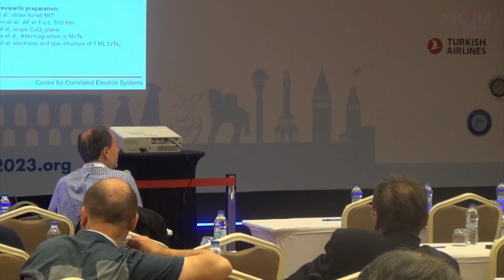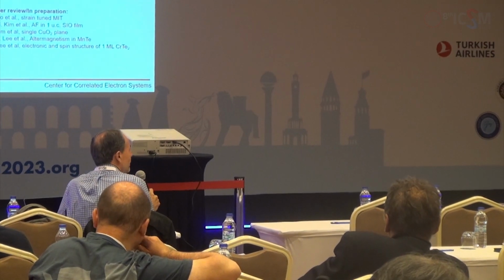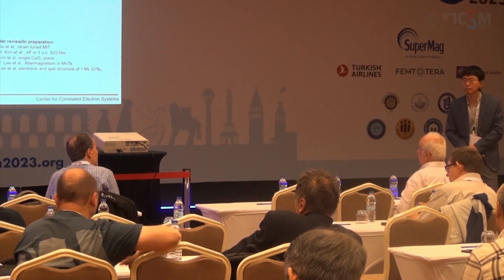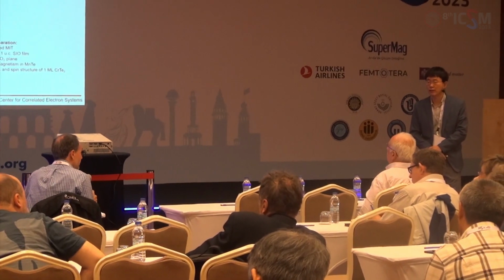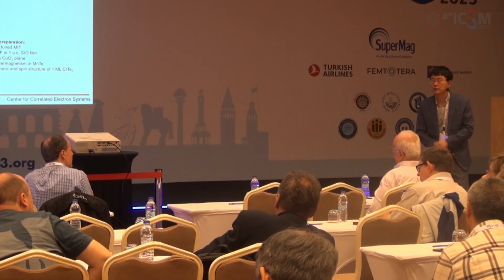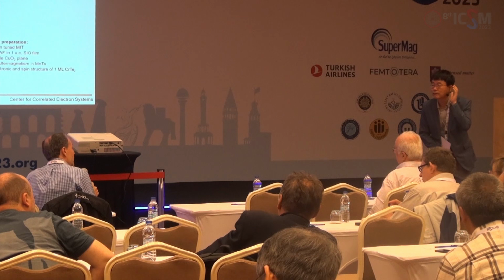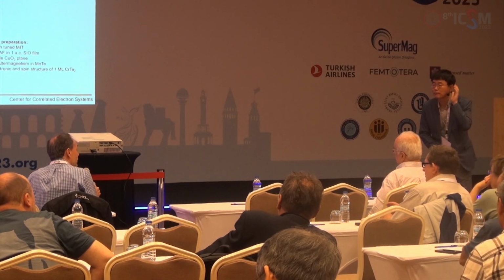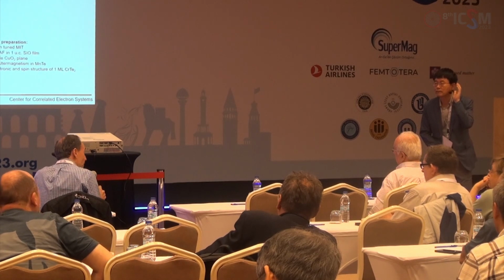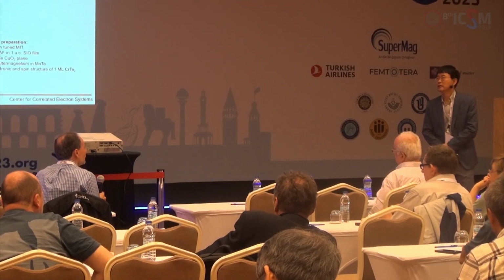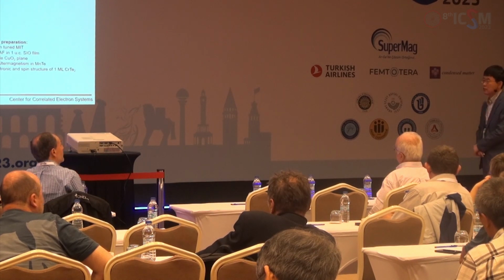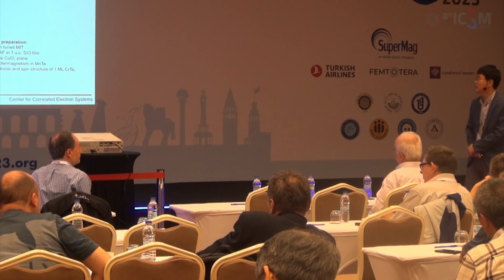Very nice. Maybe what you're demonstrating is that when you have one unit cell, you have an incredibly strong effect from the substrate. I'll give you an example. We talk about layers, one unit cell layer that you put on strontium titanate versus calcium titanate. Have you taken into account that strontium titanate is a non-stoichiometric material and calcium titanate is stoichiometric, for example? In terms of oxygen content, you're talking about?